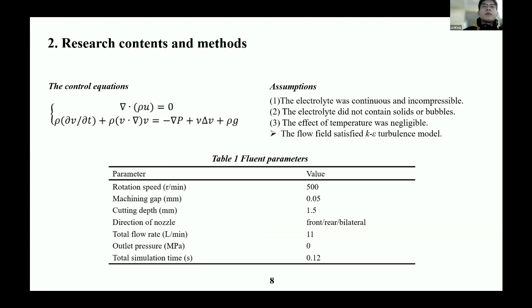In order to simplify the simulation process, some assumptions were made to the simulation model. The first is the electrolyte was continuous and incompressible. The second is the electrolyte didn't contain solids and bubbles. The third is the effect of temperature was negligible. The flow field satisfied the turbulence model. The mass equation and the momentum equation of the simulation process are shown in the figure. The parameter settings for the simulation are shown in Table 1. The total simulation duration is 0.12 seconds, which is exactly the time it takes to rotate one cycle.